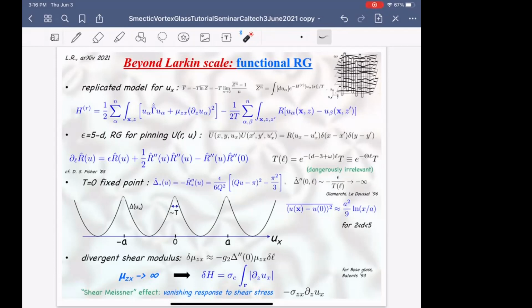The upshot of this RG analysis is that you get an RG flow equation where disorder is relevant below five dimensions, rather than below 4 dimensions. That's because the disorder is correlated here, so it's much more relevant per unit of dimension. So below 5 dimensions, you can do an RG epsilon expansion for the pinning potential, and its effect is summarized by this flow equation.